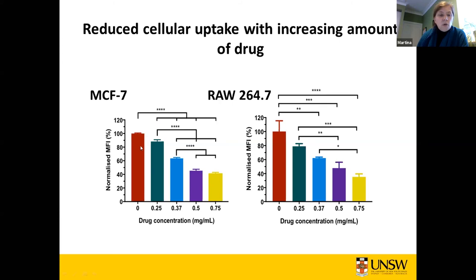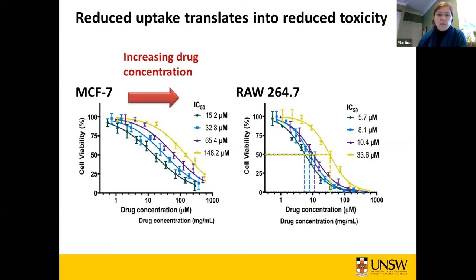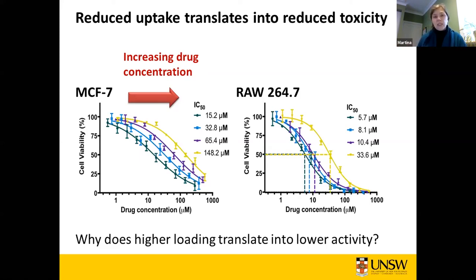So here, if we don't have any drugs, we set the uptake to 100%. And the more drugs we put in, the less uptake we have. And that's across several cell lines. So obviously something is happening. If you put nanoparticles in there, your cells don't like the nanoparticles anymore. And of course, the more drug we have, the less toxic the whole thing became because the less nanoparticles are taken up, the less drug we get inside. So this is not really what we plan to do. We want to have a nanoparticle that has a really good uptake and we deliver a lot of drugs inside.